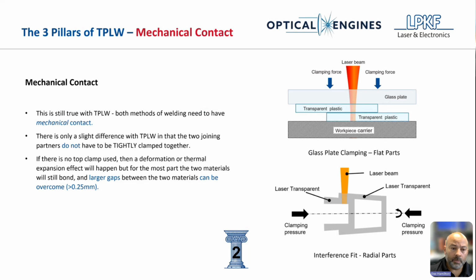Mechanical contact, like I mentioned, still needs to be held. With flat parts, it's easy to clamp with a glass plate, barring there's no features on the top of the part, etc. In some cases, you can do some machining of certain types of glass, quartz glass. You can grind borosilicate, so on. But it's very expensive and cumbersome and prone to chipping and cracking. So typically a glass plate's used for flat parts.